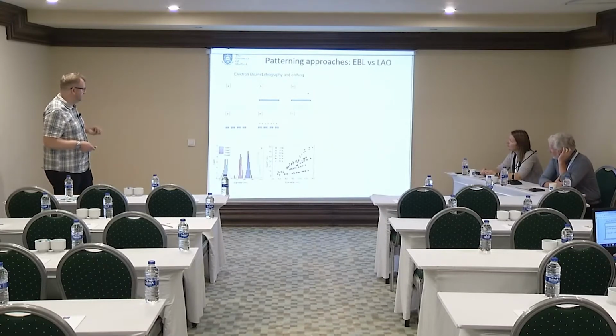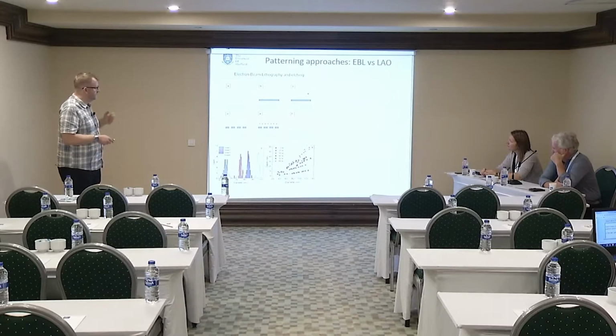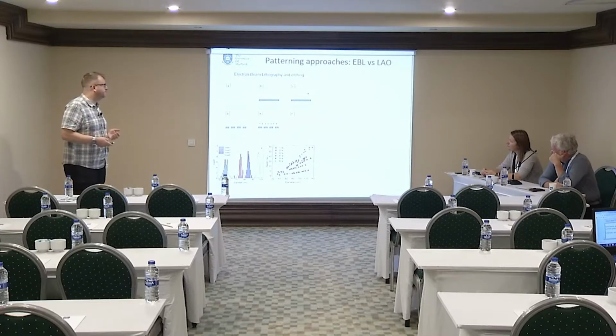So the tuning parameters that we need for that: we have the strength of the E-beam, the dose is going to affect the kind of exposure that we get. And also the drawn size is going to affect the depth eventually that we get. So larger pits are probably going to etch further when we do that.